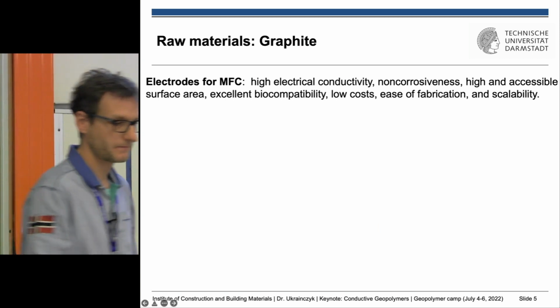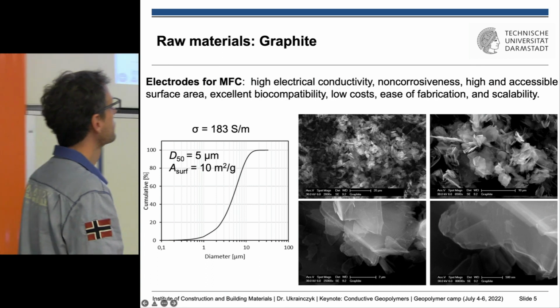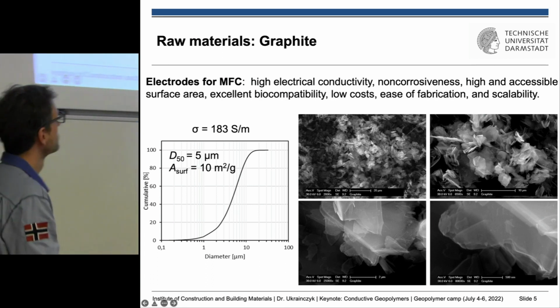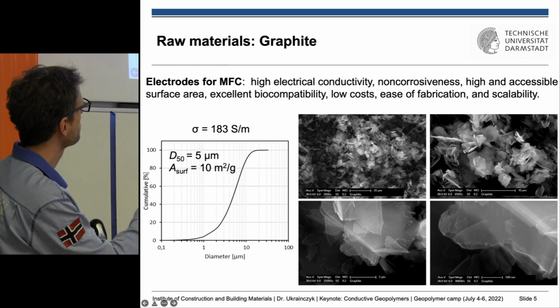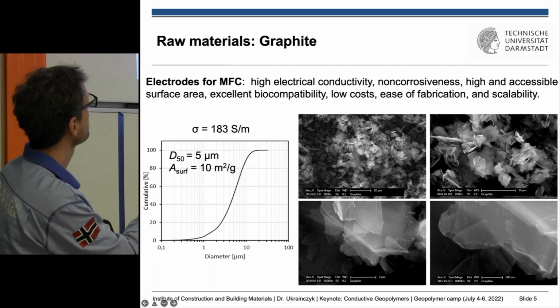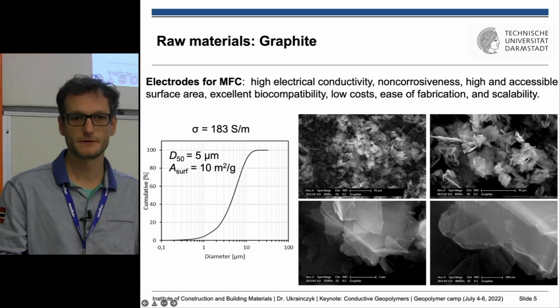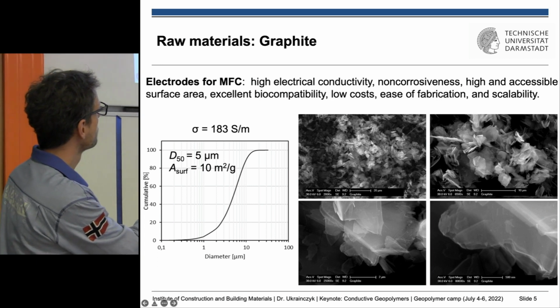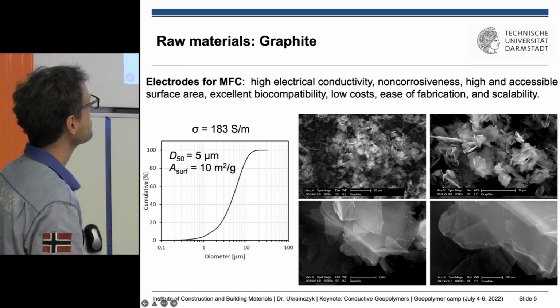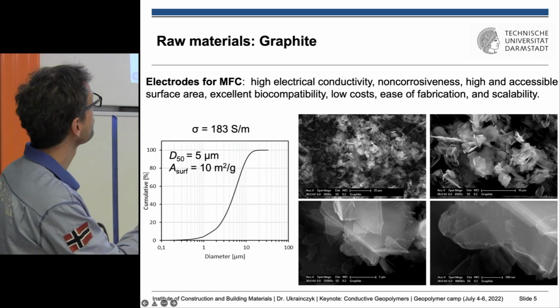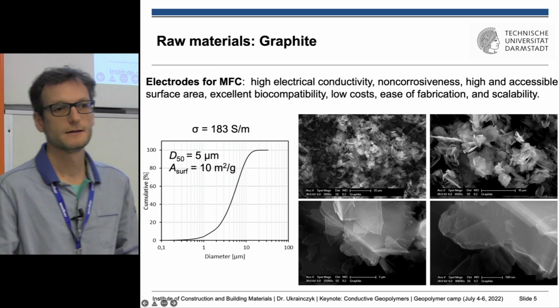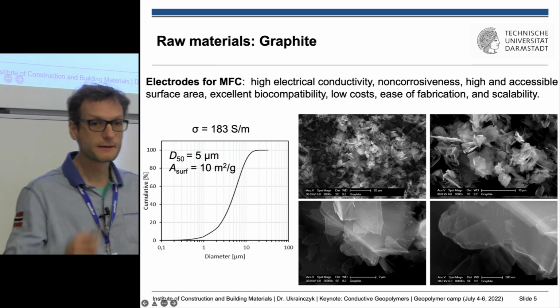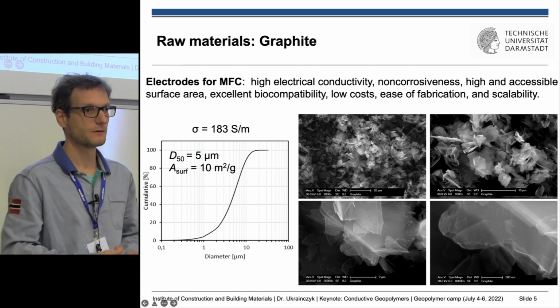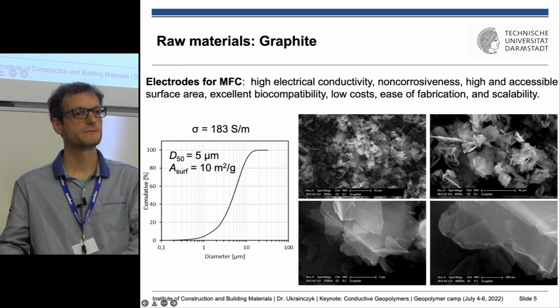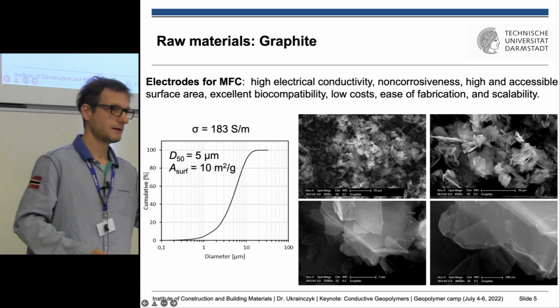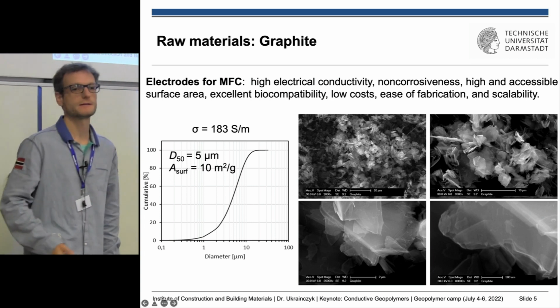So now the graphite. This is a German product we took, and they exfoliate already the graphite, so it has fine particle sizes. So this is the surface area. D50, the median, is 5 micrometers, but we also have particle sizes below 1 micrometer. And here I would say that in microbial fuel cells, they use graphite. But graphite, you also need to bind, to make the graphite rods or plates, you also need the binder. So they use different kinds of binders, maybe resins. But an idea here is to use geopolymer as a binder to make the electrode.